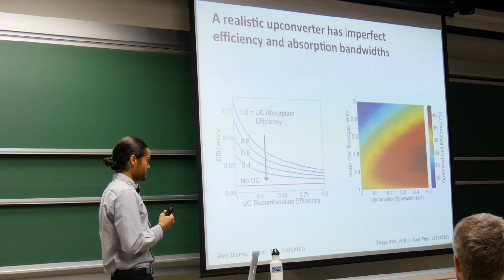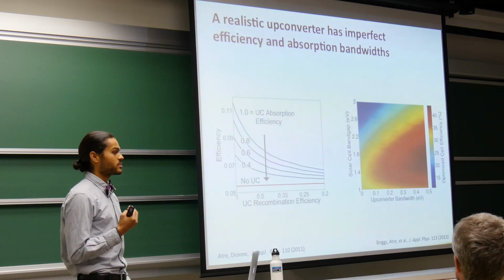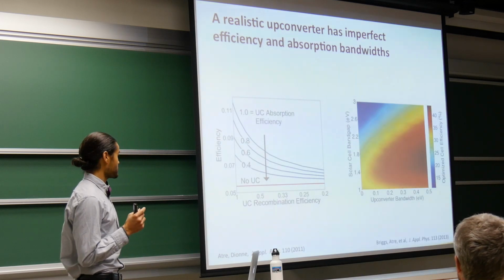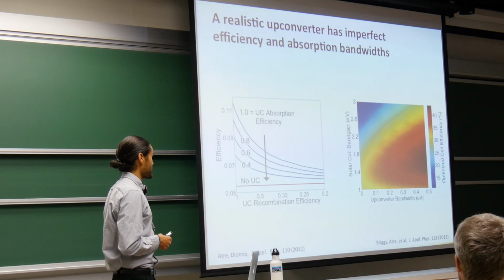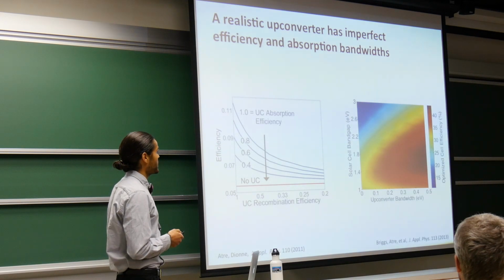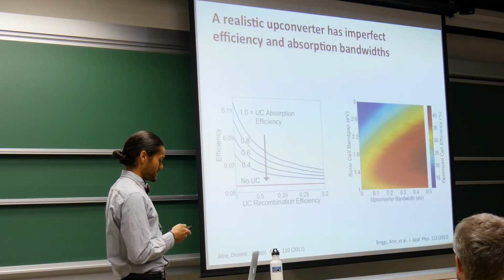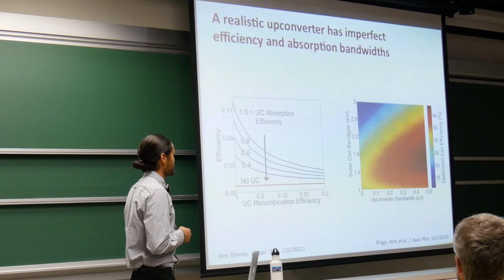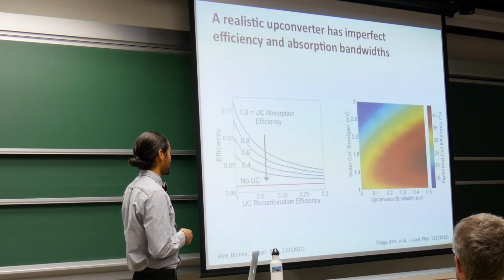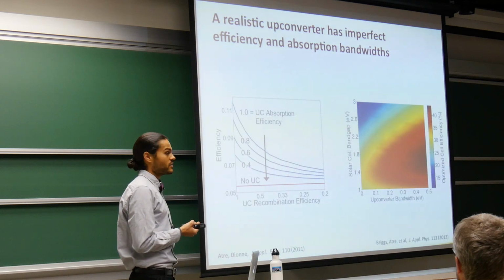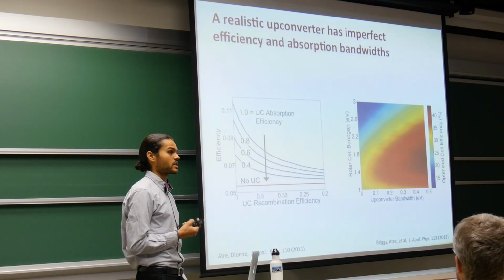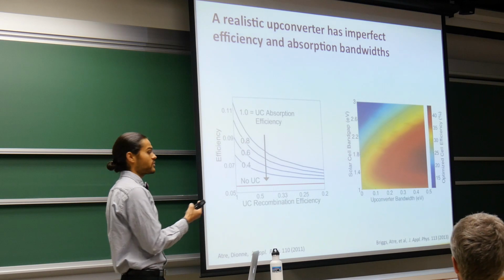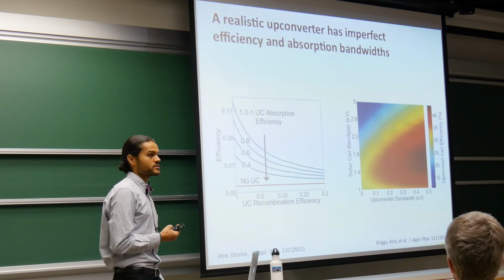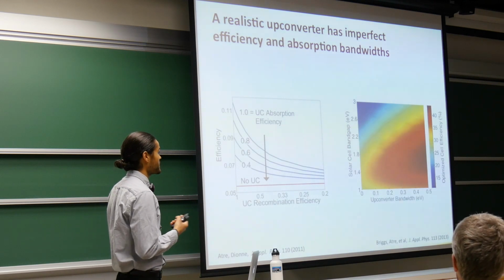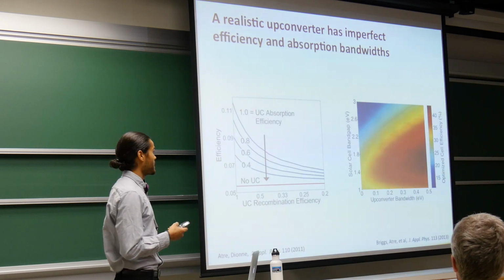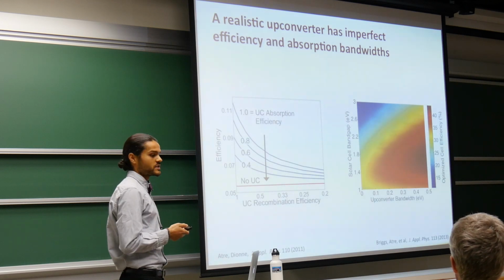But more interestingly, we also consider the fact that an upconverter can only absorb over a narrow bandwidth of wavelengths. So in this plot of optimized cell efficiency, here we have cell bandgap on the y-axis and upconverter bandwidth on the x-axis. And you can see that an upconverter bandwidth of 0 would correspond to the Shockley-Queisser limit. Now, even if we increase the upconverter bandwidth by 100 millivolts or a few hundred millivolts, we can see a very substantial increase in the combined device efficiency of about 5% or even more.